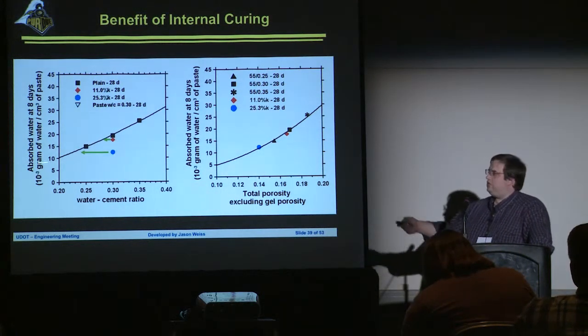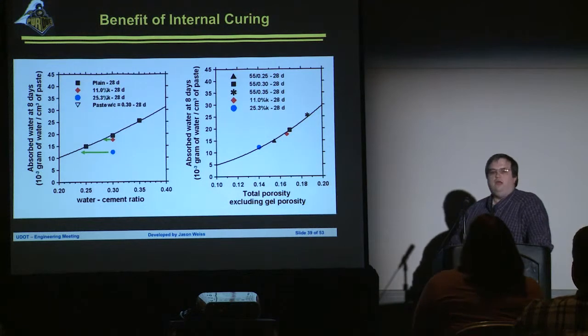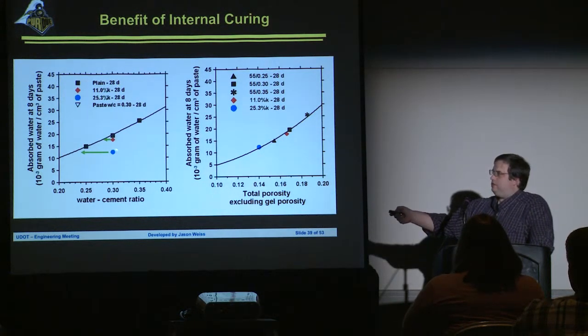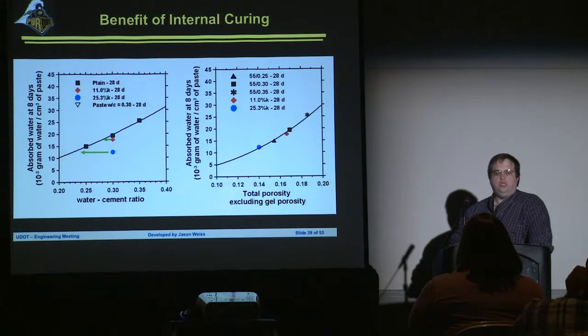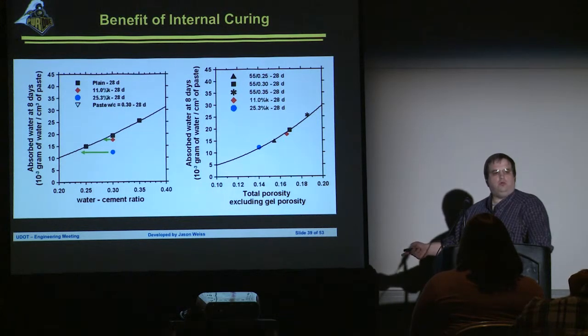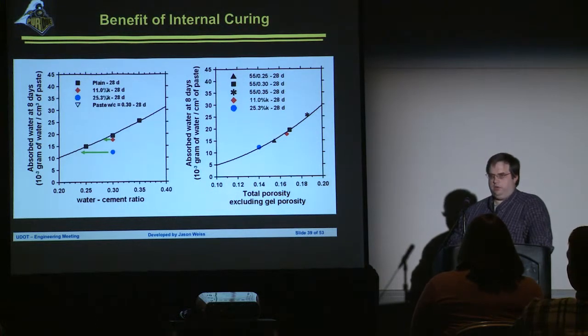What is really interesting is let's look at this blue point. This blue point is our internally cured concrete. So it's cast at the same water to cement ratio as this one, but it performs like a lower water to cement ratio. So it's cast at a 0.3 water to cement ratio, but it behaves like a 0.23 water to cement ratio. You may say, well, wait a second, how did this all happen?